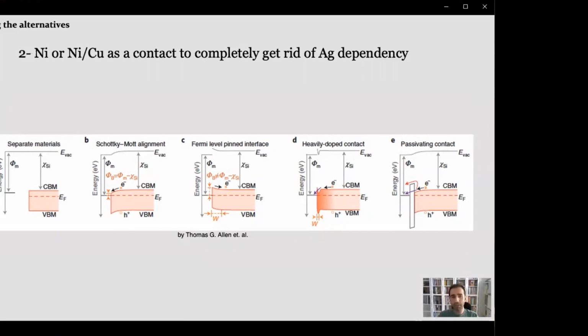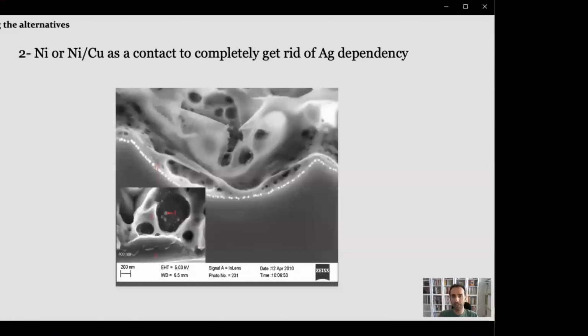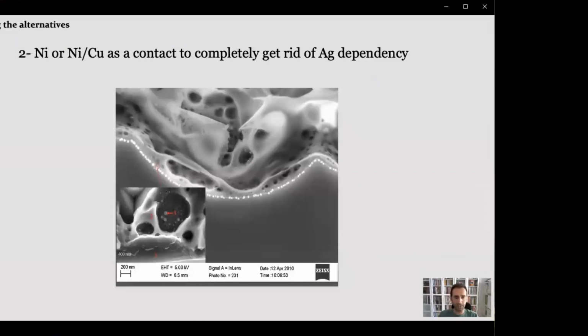About passivating contacts, there's another hypothesis that when a thick film paste is printed and fired, there will be a residual glass layer between the silver bulk and the silicon itself, and that will act as an insulator layer in between, number one in this inset picture. However, to be able to obtain a continuous and uniform residual glass layer, material engineering needs to be addressed, such as sintering of the nanoparticles in the paste, that I will not go into so much detail because it's a topic in itself.